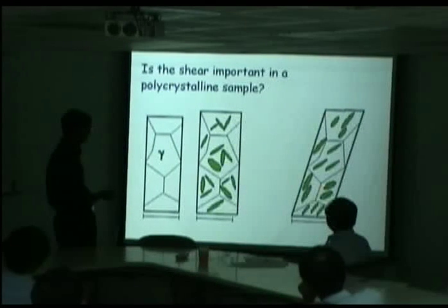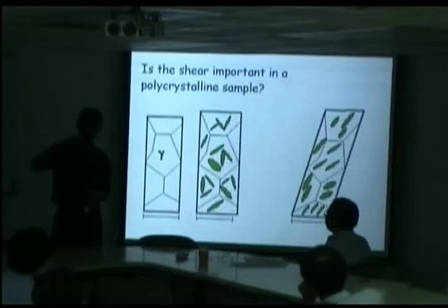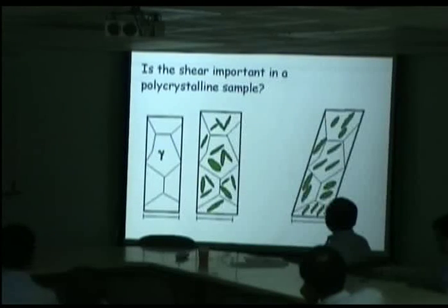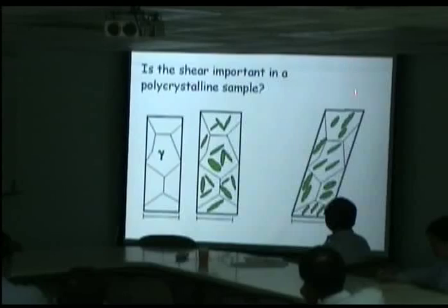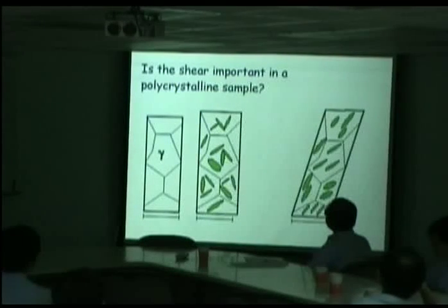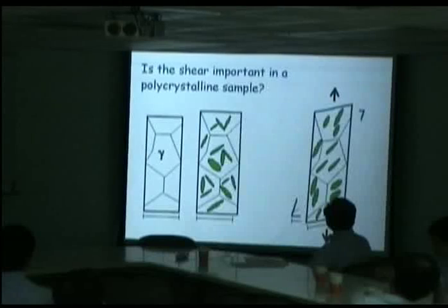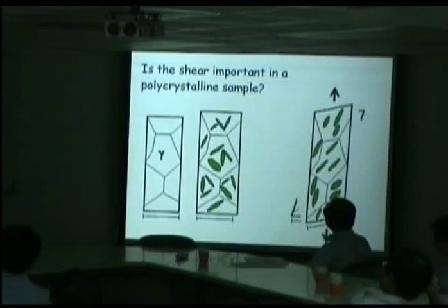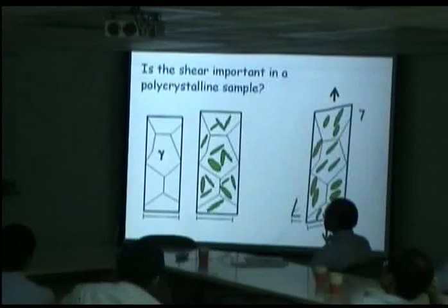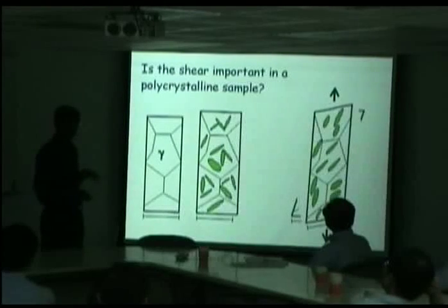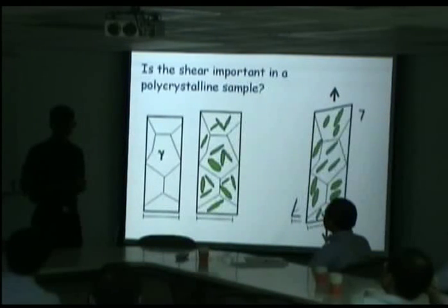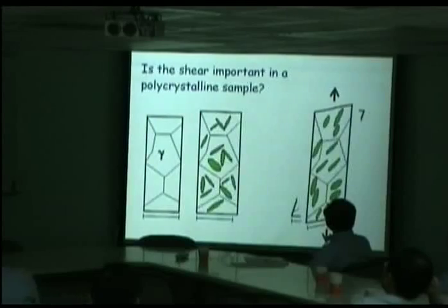So here the martensite is not forming at random, but it is forming in a preferred orientation, and that's why we shear the whole shape of the polycrystalline specimen. And if this is in a tensile testing machine, we will have a rotation as well. So we see an elongation of the specimen caused purely by martensitic transformation. So I'd like to calculate how much elongation we get if the whole of this austenite transforms into martensite in the right orientation. And remember that we are talking about polycrystalline specimens.